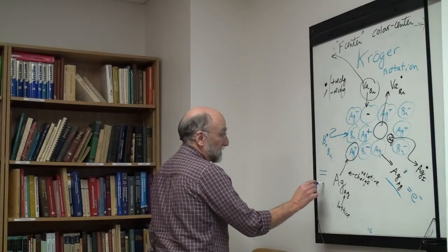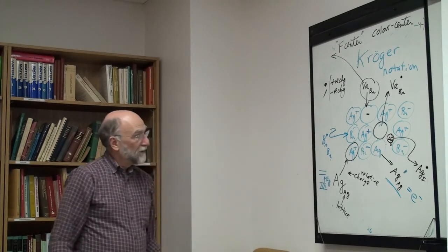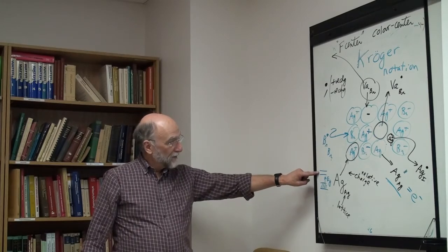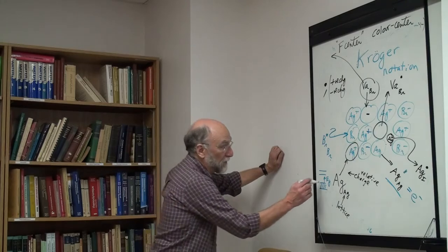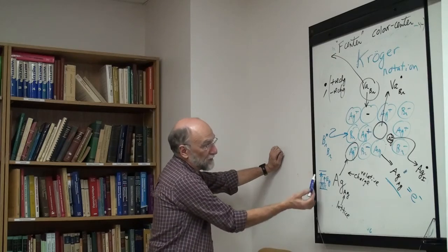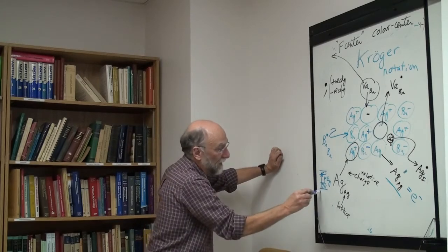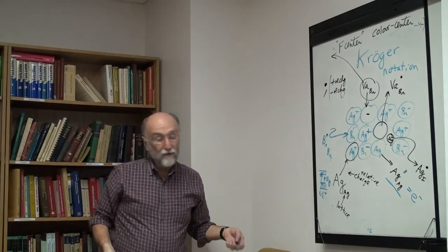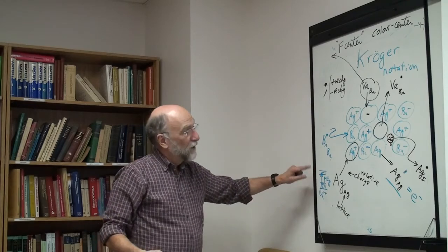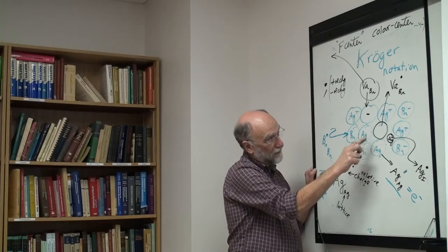If you consider the band structure of silver bromide, here you have the valence band, which is normally full. This is your gap here, and up here you have your conduction band. These electrons in the valence band are the electrons which are on the bromines. The conduction band is empty, the extra space up here. If an electron moves from the valence band up to the conduction band, this forms an electron which can move through the crystal, and an electron hole which can move through the crystal. You know your semiconductor theory, but this promotion of an electron from the valence band to the conduction band, in terms of this model, is simply the electron from the bromine popping up over to here.